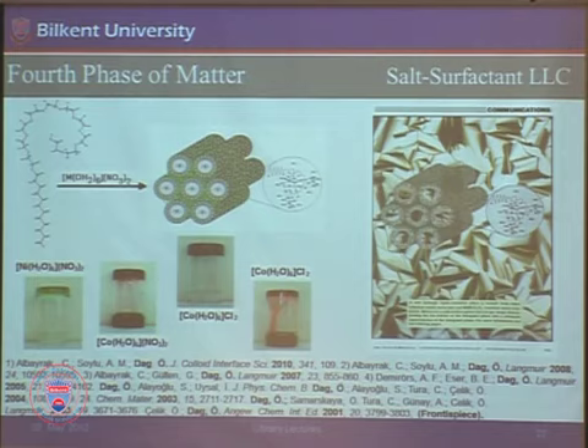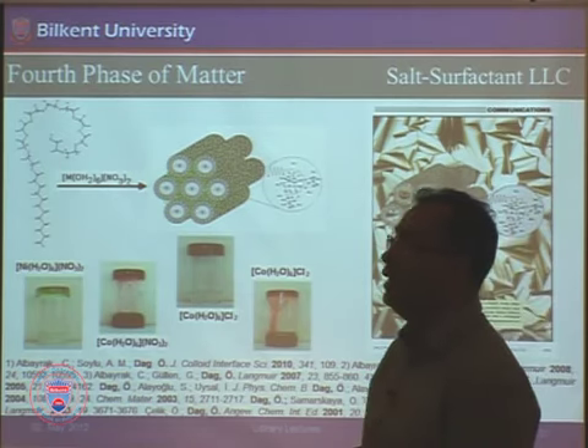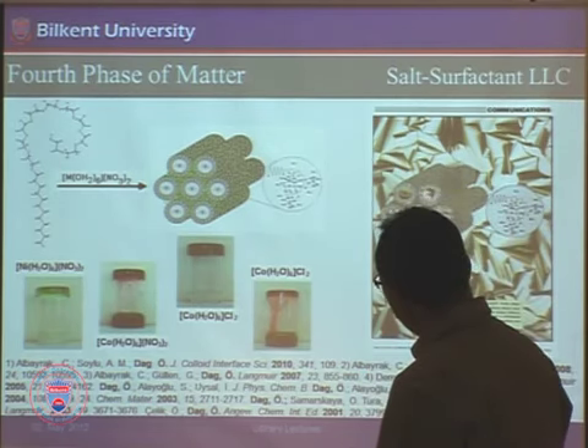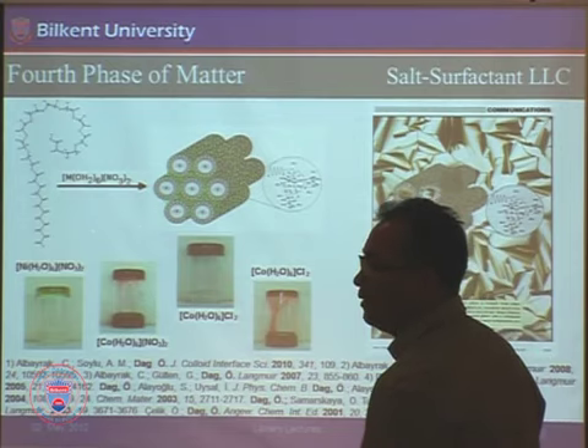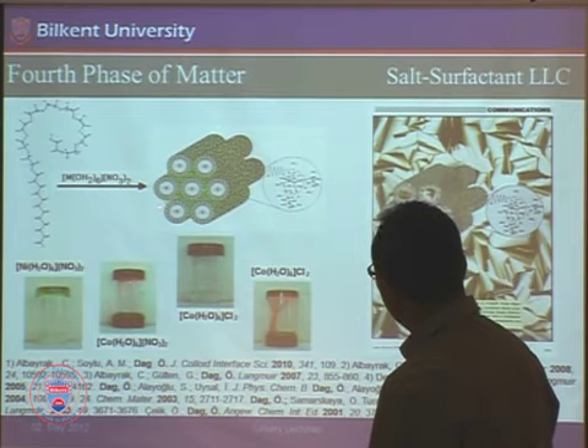A solid can be used like a solvent, basically. Okay? And that was highlighted in Angewandte Chemie that year. I think this was the first paper in Angewandte Chemie from Turkey. Okay? So you mix those two, you get these surfactant molecules organized as tubes, and in this polar region between them, you deposit these ions. These yellow, green dots are ions, basically. But these ions are not in the core. The core is water-hating, so those ions cannot go in there. So you are confining those ions in certain domains of these structures.